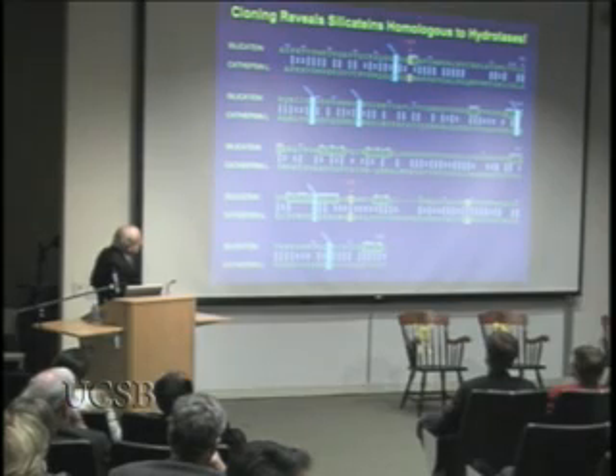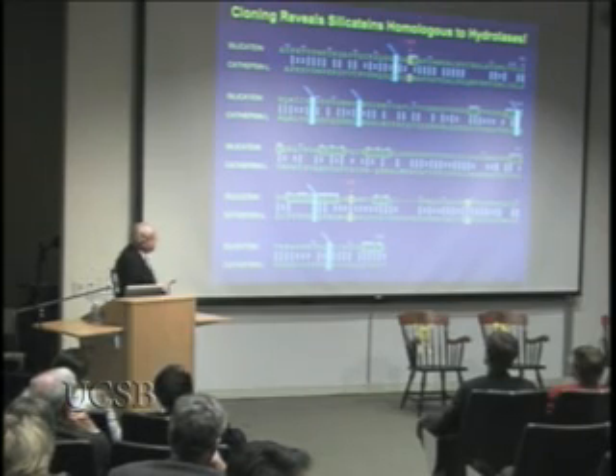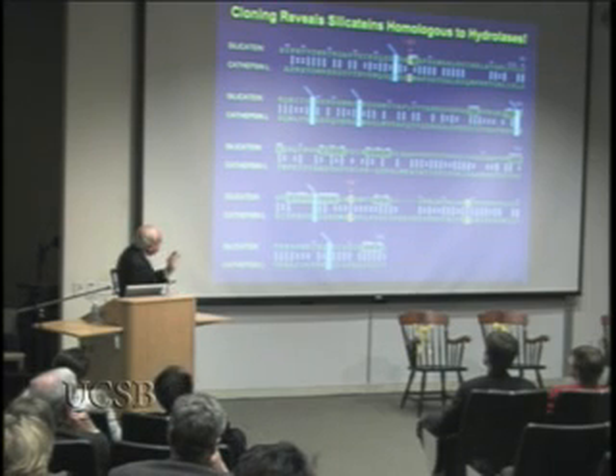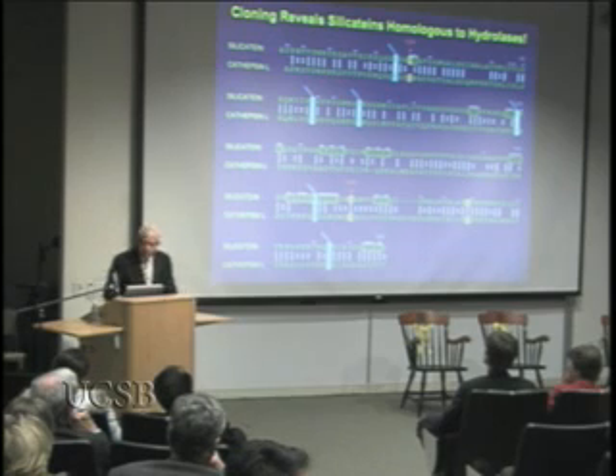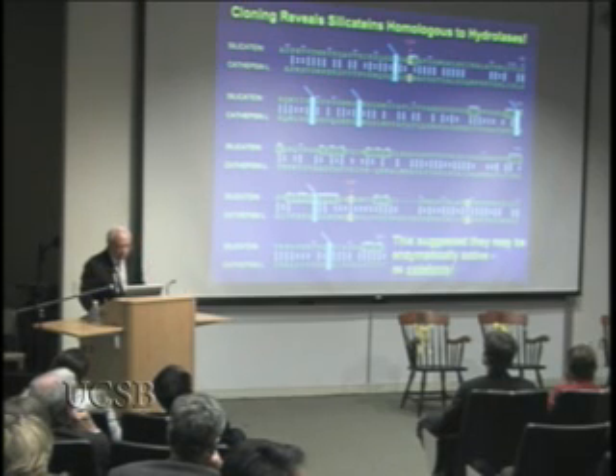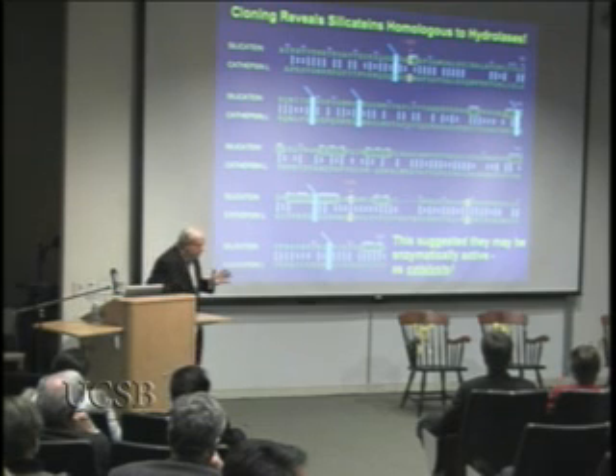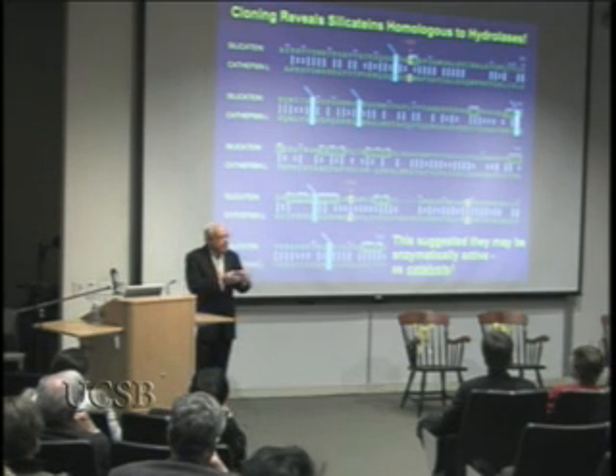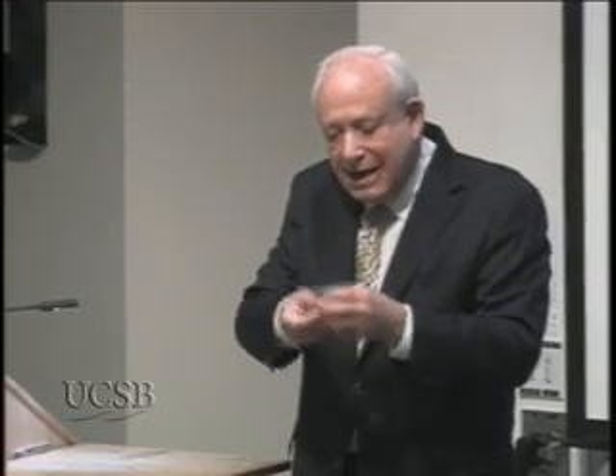And in fact, we find that the amino acids that are responsible for the catalytic activity of the enzyme are present in the same position with no change in the silicatine protein in the sponge. This suggested for the first time in the 200 years of study of biomineralization that a protein found inside a biologically produced mineral might actually be functioning as an active enzyme, a catalyst, rather than just simply a passive template like a cookie cutter guiding the deposition of the mineral. We tested this hypothesis and found it's correct.